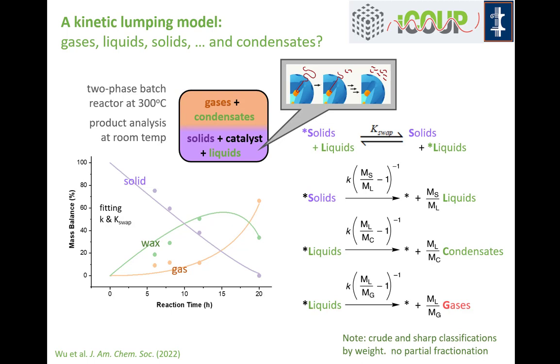This is the beginning of a reactive separation model that accounts for the two-phase nature of the catalyst and reaction mixture. With only two parameters we're predicting three curves, and we don't start making gases until the solid is gone.